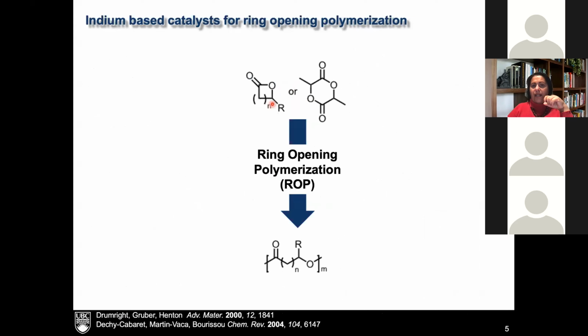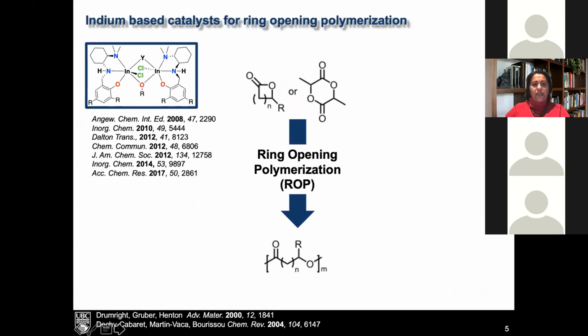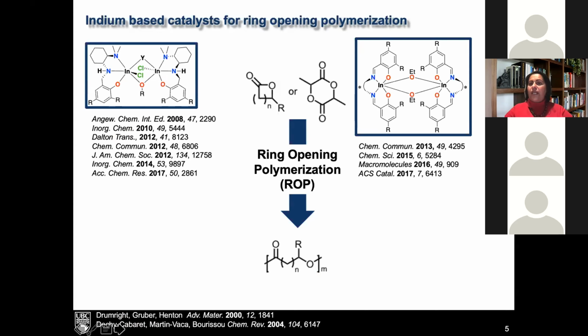In this case, I'm showing you a lactone here, and a specific lactone, which is a lactide, and we're carrying out ring opening polymerization, ROP, to generate a polyester. And we have looked at a lot of different aspects of this reaction and this catalysis with indium chemistry. I'm really going to just give you a highlight here and then give you little tastes. So we started off with these dinuclear indium complexes, and this motif comes up again and again, where indium, because of its larger ionic radius and because of its Lewis acidity, actually tends to aggregate. And one of the keys to understanding and controlling indium reactivity is controlling this aggregation. We have then worked on developing chiral analogs of this work. And this is work that was initiated and really worked on by a Sri Lankan student of mine, Dinesh Aluthge.